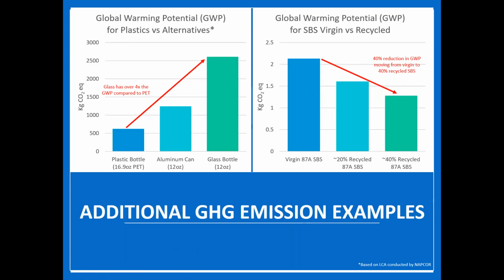So some other examples of what that looks like in terms of testing. You saw the one with the high density polyethylene, using bio-based oil and not. There's a couple other ones. There was a study done by NAPCOR, a life cycle analysis comparing plastic, aluminum, and glass. And it shows that for the same-ish amount of liquid, glass has over 4 times the global warming potential that PET does. And that's because you have to process aluminum and glass at much higher temperatures. And so the process and the amount of energy needed to heat something up that high is what causes this effect specifically.